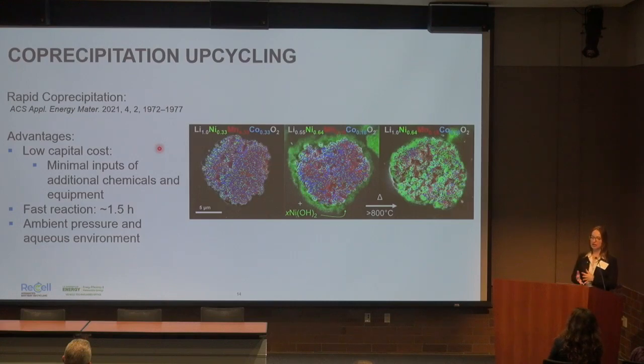And then during the relithiation process, at higher temperatures, that nickel-rich shell will diffuse into the structure of the material, basically converting your NMC 111 bulk composition to an NMC 622 composition. And while relying on this co-precipitation process, it's an aqueous-based process, and it occurs under ambient pressure. It uses the same infrastructure already present in battery manufacturing technology, such as a continuous stir tank reactor, basically a tank reactor with an overhead stir and an output valve. That's all you really need.